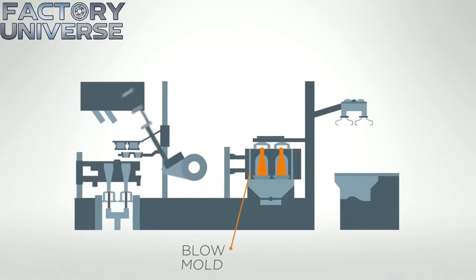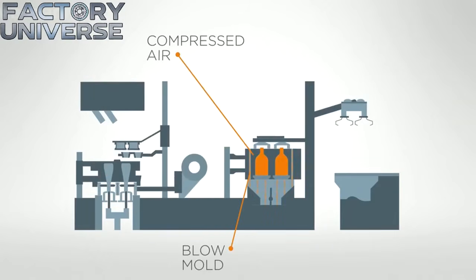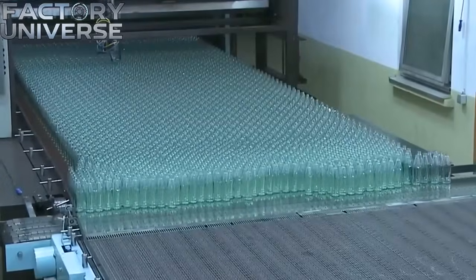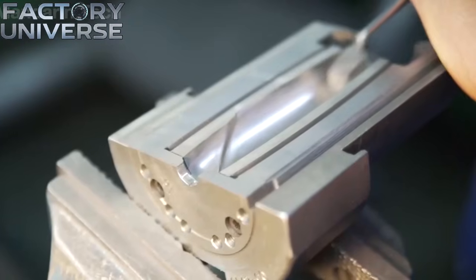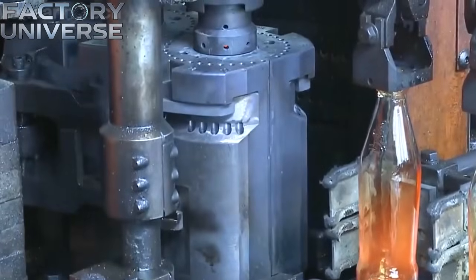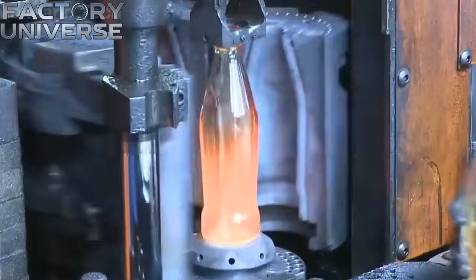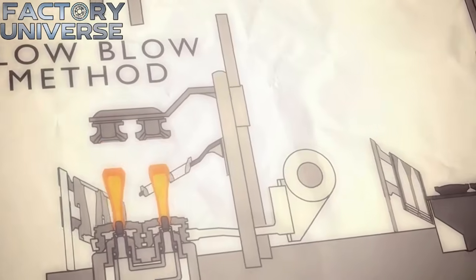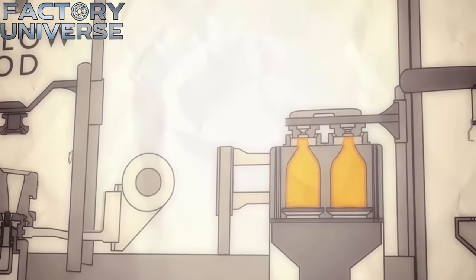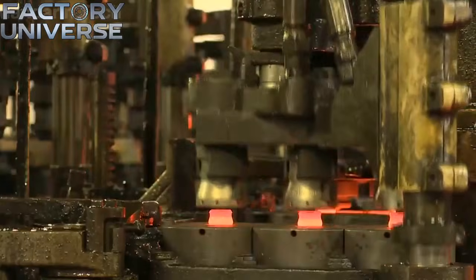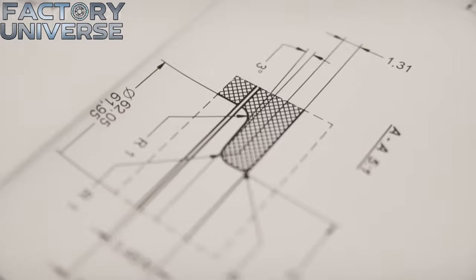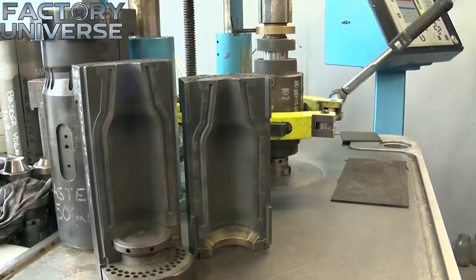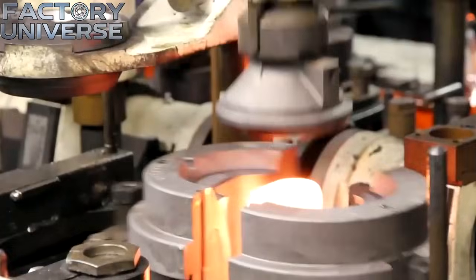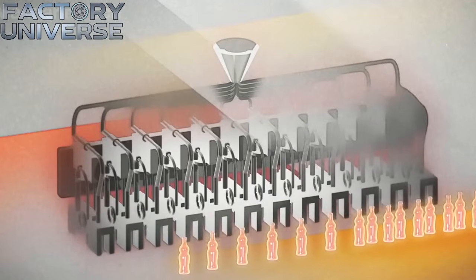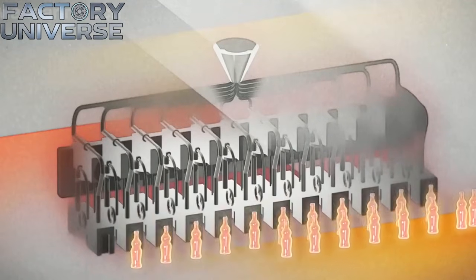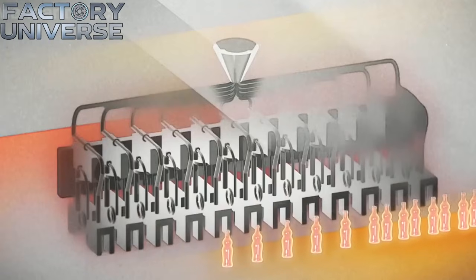Still radiating an intense heat, the parison is transferred by mechanical arms to the final mold located only a few inches away on the same line. In this second stage, another burst of compressed air is injected directly into the center of the parison, stretching the softened material until it presses tightly against every contour of the mold cavity. In just a few seconds, the full geometry of the bottle is established. It only looks obvious and effortless from the outside, but in reality, every valve and sensor is synchronized to 1/1000th of a second.